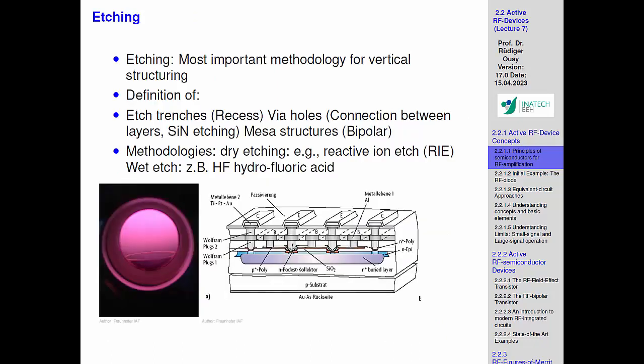So this is also not an easy process, and what is always turning us crazy these days is that this is obviously a macroscopic process. So you have a hole in the chamber, and then by timing you say, I'm waiting for 10 seconds and I'm removing one atom layer. I wait for 20 seconds, 2 atom layers. And this is of course quite tricky, because if you miss that timing, or if there's anything which doesn't belong there in the process, then the timing might not be correct, and it takes maybe 12 seconds to remove one atom layer, and then you're not connecting the structures underneath correctly, or you are over etching.